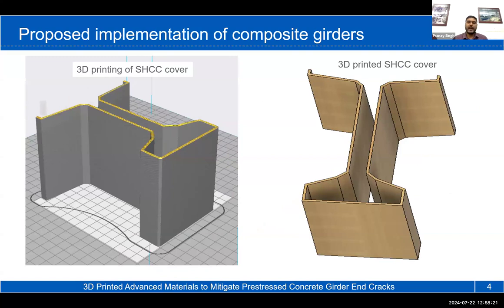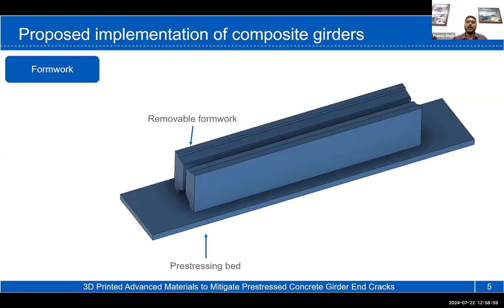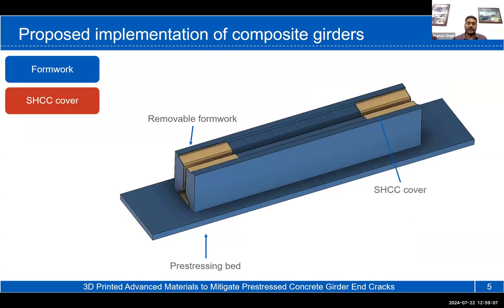As the technology matures, it could have a lot of different use cases and implementations. But at this stage, we are considering one simple method of implementing this, which has two stages. The first stage involves 3D printing of these covers. A 3D printed SHCC cover will be made either at the precaster's facility or at a 3D printing laboratory. Once it is printed, it will be cured and given time to gain strength. When it is ready, it will be transported to the precaster's facility, where they have a pre-stressing bed and the usual formwork used to create these precast girders. One feature of these 3D printed covers is that their thickness will be limited to the cover zone thickness of the girders, so that they can fit inside the formwork without any modification.